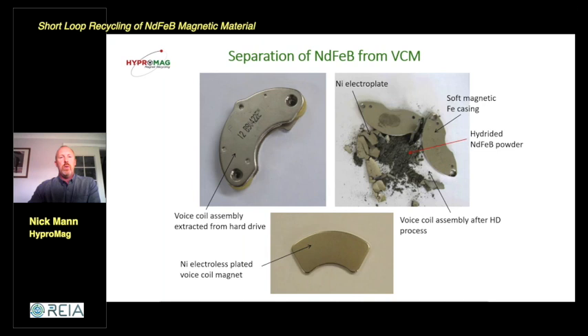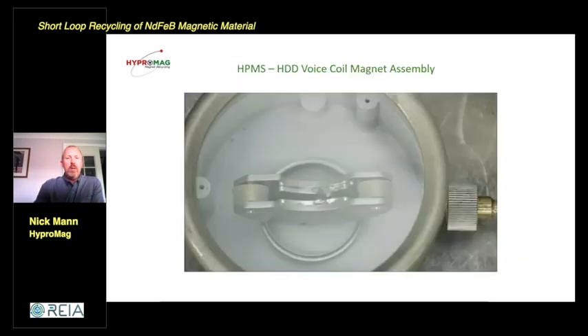And then the top right picture shows what that looks like after we've put it through a hydrogen reaction process. You can see the NdFeB, which has become more of a powder. You can see the ferrous casing, and you can see the nickel plating that's come away from the magnet. So I can show you this process. This is at the University of Birmingham, where they've put one of those voice coil assemblies into a vessel with hydrogen coming in. You can maybe just about see on this magnet where we've introduced just a bit of damage to get through the nickel coating. And that means that the hydrogen can get into the NdFeB and the reaction can initiate.